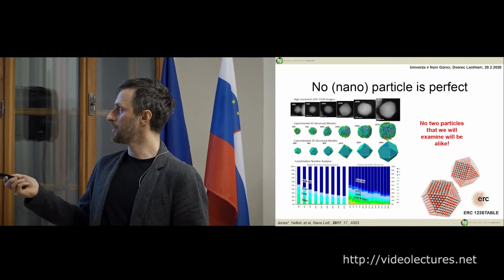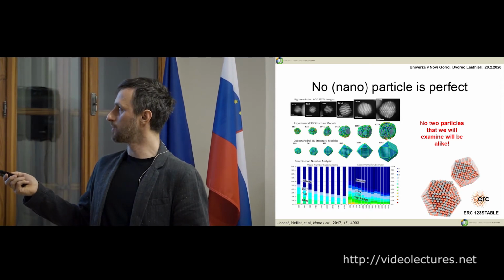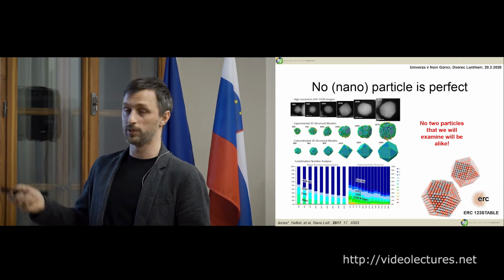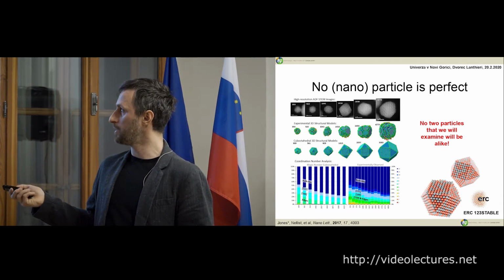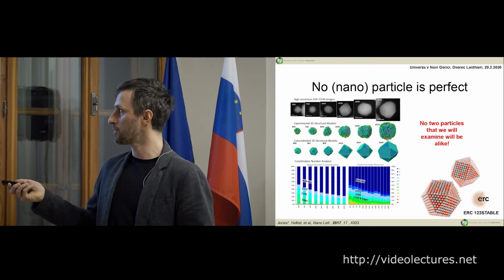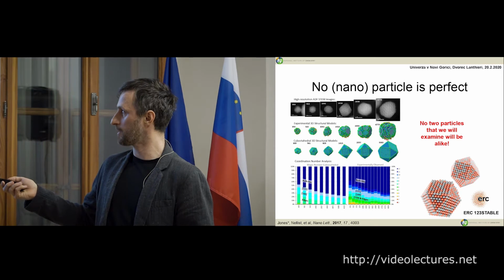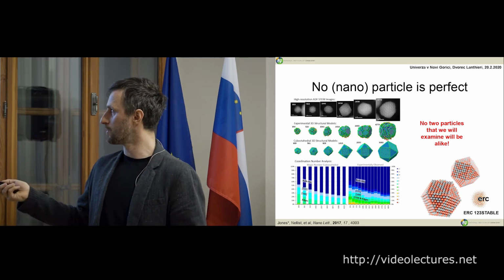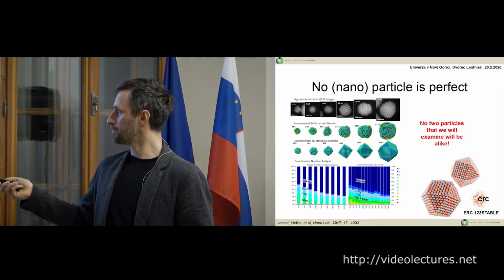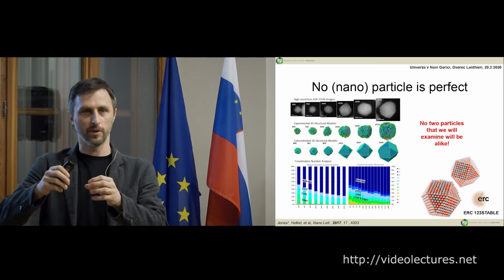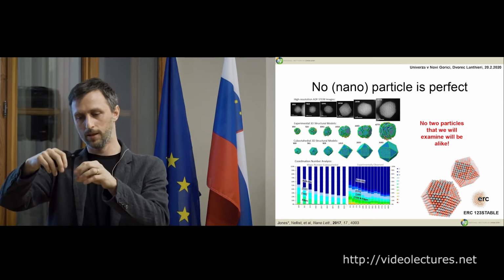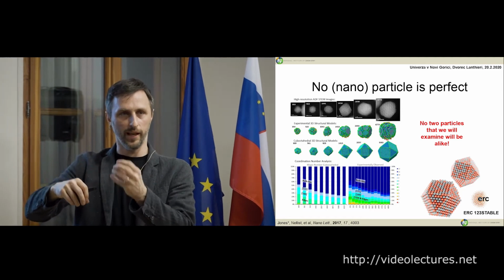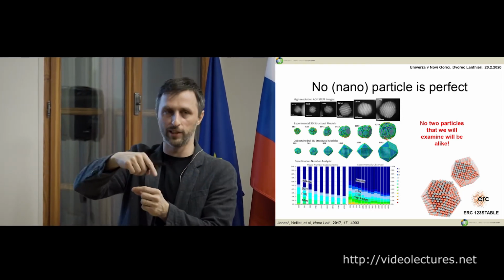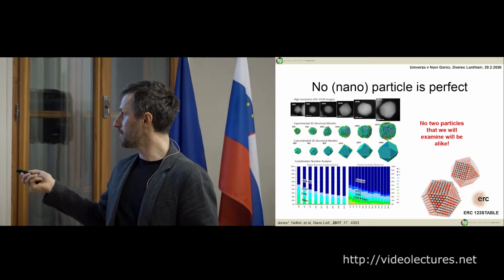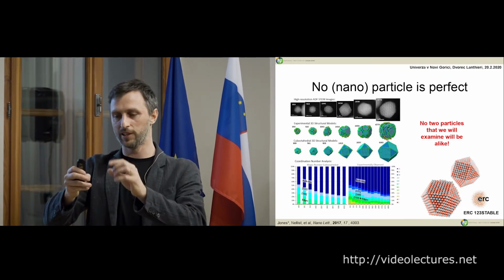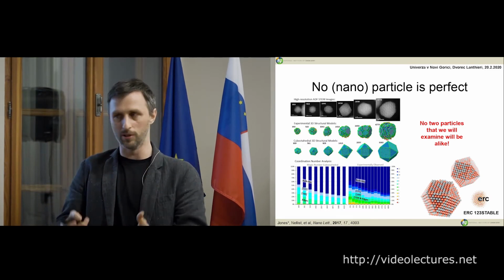So here they compare these magic number cubo-octahedra with the same amount of atoms as the real nanoparticles that we see in the microscope. And if we count how many defects they have in the coordination of the surface atoms, you compare here, this is perfect particles and this is real particles, you can see there are a lot more defects. So the coordination number is how many atoms are around one atom. You choose one atom on the surface and you count how many neighbors it has. If it's perfect, you have a lot of atoms. If it's very defective, you have not so many atoms. So the coordination number is low.